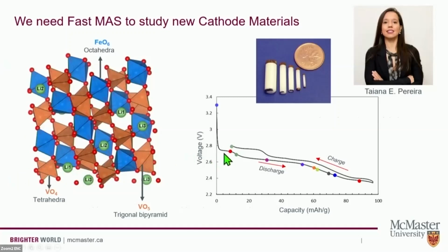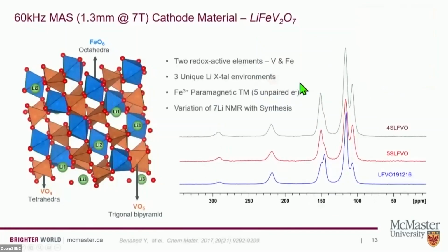And electrochemically, it's quite beautiful. It has some nice smooth plateau regions, then some phase transition regions, and it has a very nice reversible electrochemical process shown by the small hysteresis in this electrochemical cell. And at each of these data points along the curve, Tayana is going to take out the coin cell, disassemble it in the glove box, and pack it in the tiniest of these rotors in order to do magic angle spinning as fast as we're capable of in our lab.